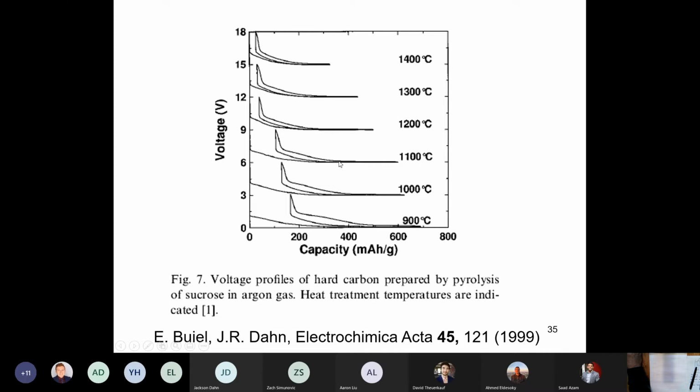So it seemed to us at the time that if a lithium atom was just adsorbed on the surface of a graphene sheet, its binding energy would be very small. That means its voltage would be very small, very close to that of lithium metal. There wouldn't be much advantage for a lithium to be on the surface of a single graphene sheet compared to being in lithium metal. Intercalated into graphite, the voltage is only about 80 millivolts. The voltage of this plateau is about 50. So it's about half: one graphene sheet compared to 2. It's absorbed to the wall of these pores.